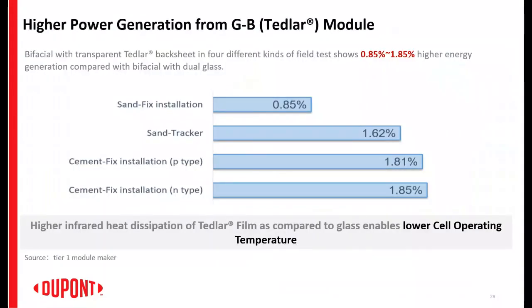One of the key requirements of any project developer or asset owner is higher generation. And this is where a Tedlar backsheet would perform better as compared to glass. This is a study done by a tier 1 module supplier, but it was done mainly for bifacial modules. What we understand is that the same concept is applicable for monofacial modules, and why a Tedlar backsheet would perform better. Ashish also mentioned that they operate at a lower temperature, and this is essentially because a Tedlar-based backsheet has better heat dissipation.